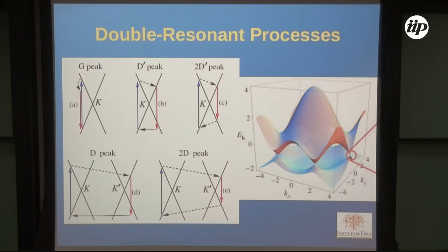You excite your electron to here, you create a phonon with zero momentum, and then you have the scattered light, okay? But today, I will not talk much about this. I will talk about the double resonant process. Double resonant processes are these guys here. So for instance, I will start with this one. We can now excite the electron here. I can create now this phonon. This phonon doesn't have a zero momentum. It has a large momentum. And then it can annihilate the electron hole pair.